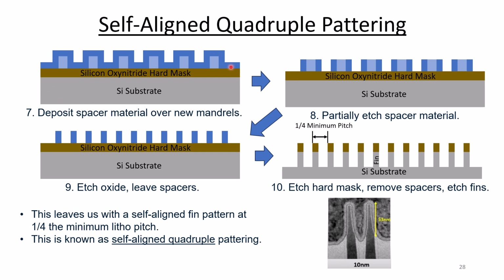So this is the same diagram. And we come over here, we etch the spacer again, and it just leaves spacer to the left and right of the oxide mandrels. Now we strip out the oxide, and it just leaves the spacer behind. We use the spacer to etch the hard mask below, and then we remove the spacer, and the hard mask is used for our anisotropic etch, where we etch the fins. And this actually gives you 1/4 minimum pitch. So this gives you something called self-aligned quadruple patterning. And all these fins are completely self-aligned with each other.